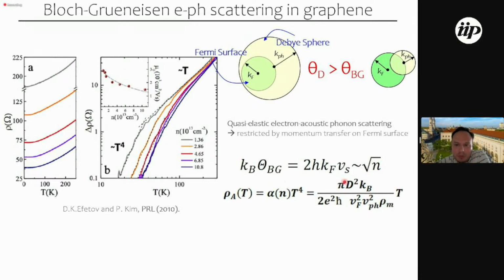And so if one now plugs this Bloch-Grüneisen temperature into the calculation for resistance, one really finds that there is a T to the 4 component at low temperatures, which then quickly becomes a linear T component if you go to higher temperatures. And so now the question, of course, is how can we translate these findings to twisted bilayer graphene?